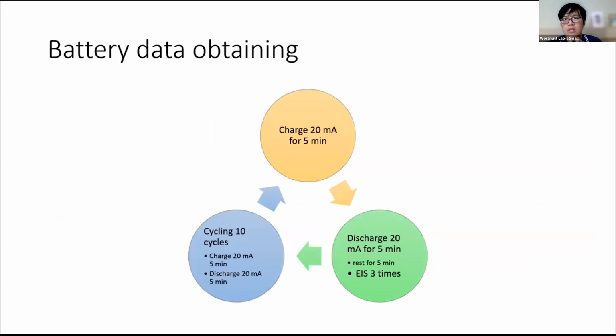To obtain the battery data, the fabricated battery was operated using the procedure shown in this slide. At first, the battery was charged with a current of 20 milliamps for 5 minutes. Then it was discharged at 20 milliamps for 5 minutes and tested with EIS 3 times. After that, the battery was cycled with the same charge and discharge conditions for 10 cycles. Then we repeat the process of testing EIS again.